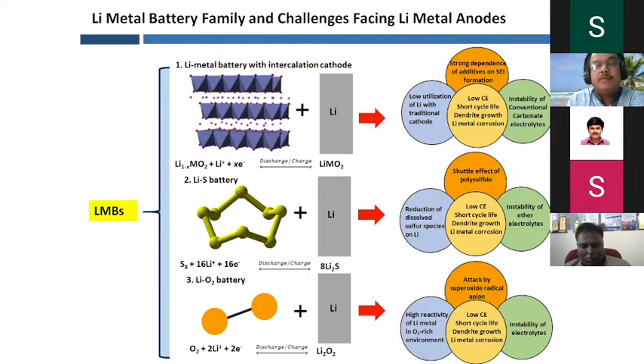A lithium metal battery with intercalation cathodes will come across low coulombic efficiency, short cycle life, dendritic growth, and lithium metal corrosion. Almost everywhere you can find these problems. This comes mainly from the lack of a suitable electrolyte. We have other problems, leave it. Only in the yellow circle, you can see almost all the technologies require a good electrolyte; only then can you think about fabricating and evaluating these three types. My idea is to focus on the present lithium metal battery, then touch upon the lithium-sulfur battery. The lithium-air battery is not that mature. So we have to think about these two technologies.